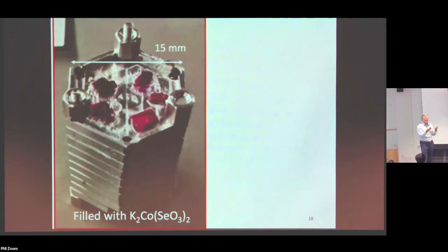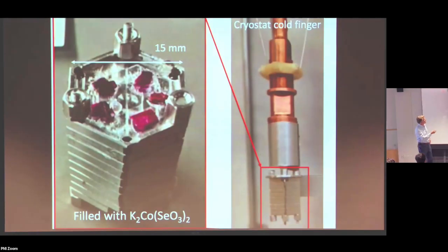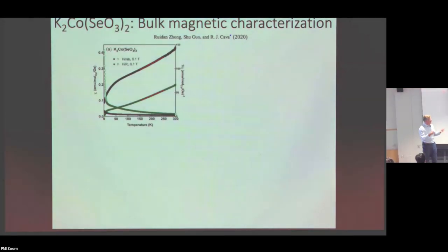And we use the fact that neutrons barely interact with material, and so I can use some aluminum, and that's perfectly fine. The neutrons just pass through it. I will see some signal from phonons and from Bragg diffraction, etc., but I can manage to subtract that out or handle it in some way, because my phase space for scattering is large. It's four-dimensional. I've got Q and energy, and this will just live somewhere else in phase space. That's fine. I would like to minimize it, but I can use this kind of methodology. Put it on a cryostat. Maybe put it inside an electromagnet, and we are off to the races. But first, we need to know something about the material, and this we do by regular thermodynamic measurements. And here I'm showing you just susceptibility versus temperature for this triangular lattice Ising system.